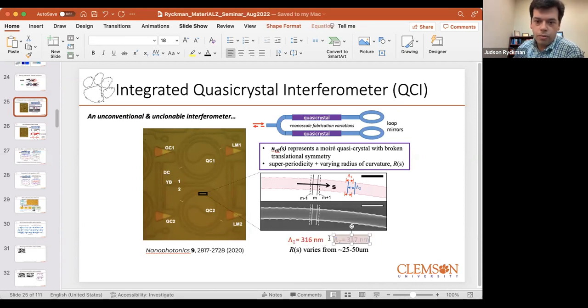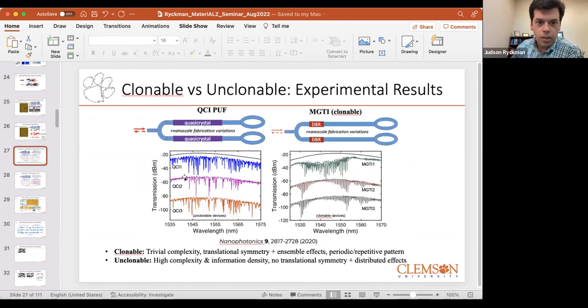But when you mix it with another, you can imagine two competing Bragg mirrors that begin to overlap with one another. So you not only have the band edge effects that occur. When we measure the spectrum, all of the disorder really shows up in this window. If we measured it at, say, 1700 or at 1300, it would look more clonable, because we're far away from the Bragg window, away from the band edges. So that is an important nuance that we might have missed.